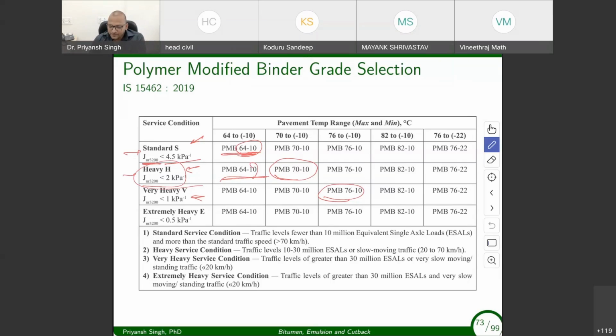But here in India, we are using a lower quality additive material. They are mostly truck tires, which already have around 20%, even more than 20%, of natural rubber in them. That reduces the quality of the crumb rubber modified binders. This polymer modified binder should not be compared with the crumb rubber modified binder, and in my opinion, the use of crumb rubber modified binder needs to be decreased, also because there is very little quality control when producing vehicle tires.